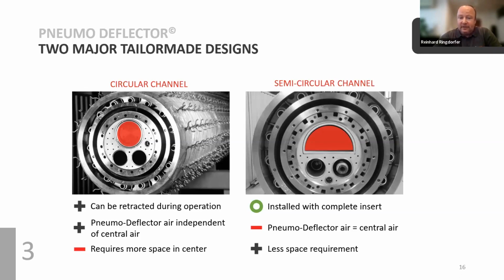This is installed inside the burner as a complete insert, so there is no way to take it out separately. So if there is damage, you have to take out the complete internal of the burner. The deflector air is used from the central air, so you can adjust only central air and deflector air together, not separately. But on the plus side, you have less space requirement. It's much smaller than the other execution, and therefore you will get a smaller kiln burner.